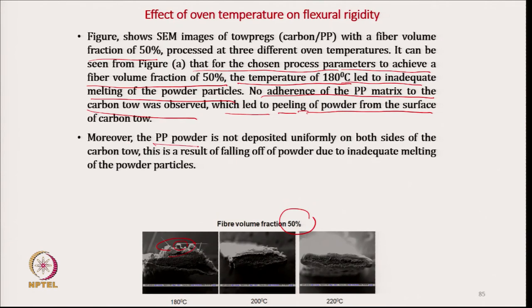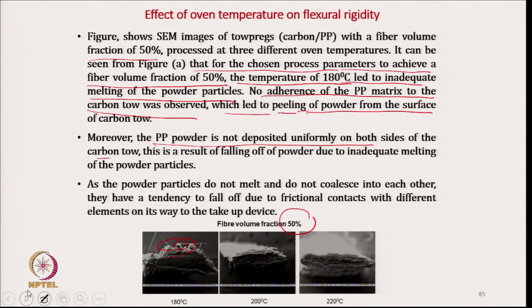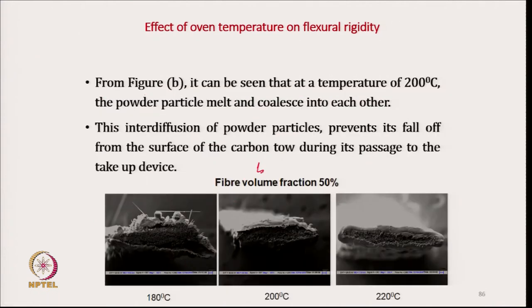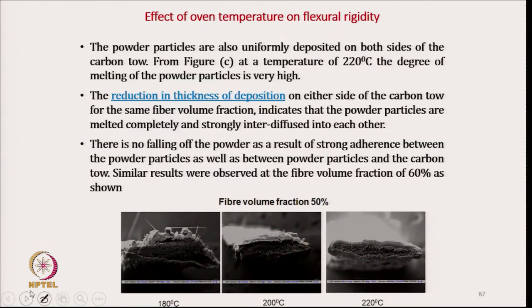And also the PP powder is not deposited uniformly on both sides of the carbon tow. It is not uniform because of the improper melting of the polypropylene. And in figure B, which is at temperature 200 degree Celsius, powder particles melted properly, and interdiffusion of powder particles was there, which prevents it from falling off. And at 220 degree Celsius, the degree of melting is very high, and the reduction in thickness, as I have already mentioned.